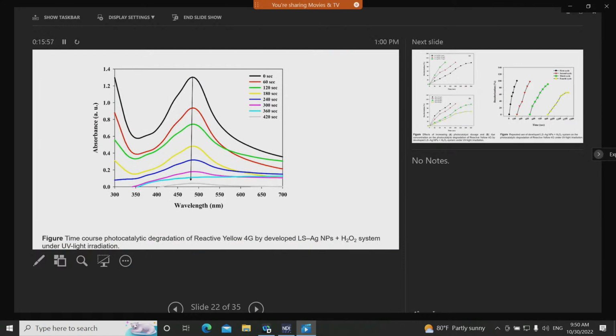This is the time course photocatalytic degradation of the dye developed by the LS-Ag NPs, H2O2, and under the UV light irradiation. As we can see here, there was a decline in absorption peak intensity at 485 nanometer, and the complete elimination of the peak was observed almost in 420 seconds, that is about 6 minutes, which indicates the degradation of dye by the developed photocatalytic system.